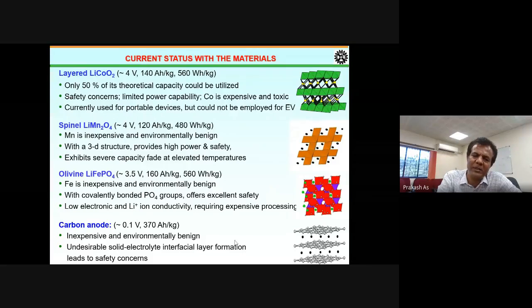And on the anode side, what is mostly used commercially is graphite-based carbon. Intercalation potential is 0.1 volt, and energy density is 370 amp hour per kg. It's inexpensive and environmentally benign. And one of the issues is the undesirable solid electrolyte interface layer.